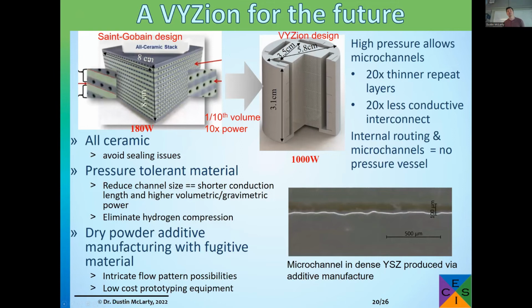So in Saint-Gobain's design, they have this ceramic block with holes on all the sides that they then needed face seals on all four sides. So it reduced the amount of seals necessary, but there still were seals, and they were very difficult seals because you had to apply this radial compression rather than just axial compression, which is usually easier to add at high temperature. So we're trying to build this assembly like you see on the right.